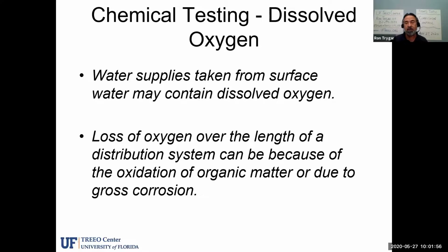So if you were to measure dissolved oxygen in, let's say, a water main that is several miles long and made of galvanized metal or galvanized iron or cast iron, if you were to start at the water plant and measure the dissolved oxygen and you got a residual oxygen of, say, 6.0 milligrams per liter, and you went 2 miles downstream on the same water transmission main and the dissolved oxygen was now, say, 2.0, and you lost 4 milligrams of oxygen somewhere, that would generally indicate that corrosion is occurring in there, because the oxygen is being used to make the rust.